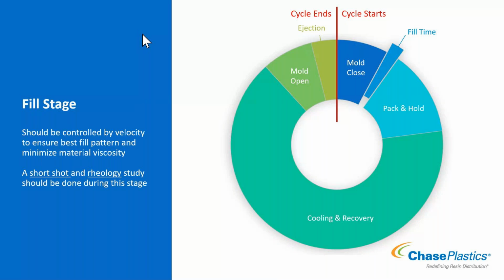So during the fill stage, as I mentioned earlier, this should be controlled by velocity, which means we need to give our machine enough pressure to achieve the set velocity. And we need to give it a little bit extra to account for material variation from lot to lot, so that we don't end up in what we call a pressure limited situation where our velocity becomes limited by the pressure well that we've allowed the machine to use.